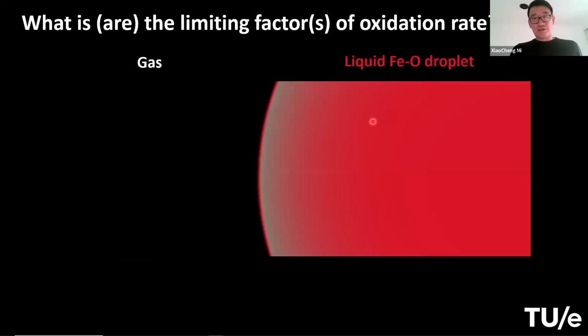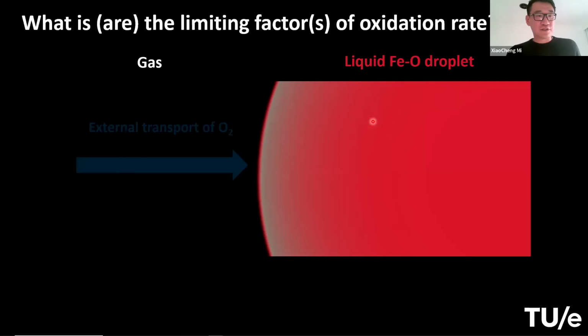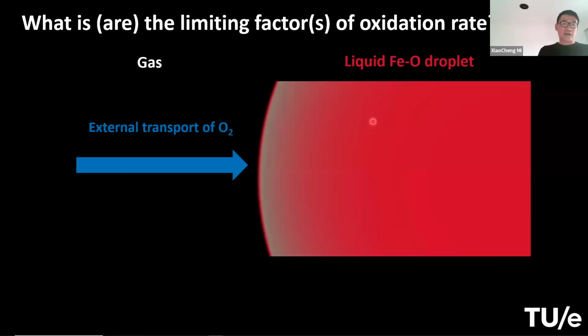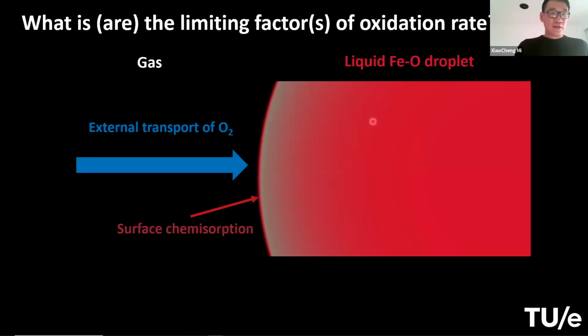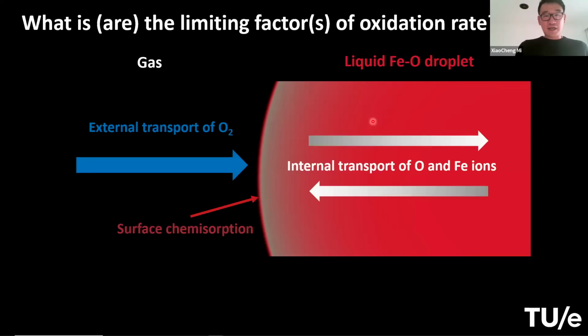And then in liquid phase, we consider the particle might be limited by a few factors, so that the oxidation rate is governed by the interplay among these factors. The first one is the boundary layer external diffusion of oxygen from the bulk gas to the iron particle surface. And then surface chemisorption is the second process. And inside the particle, there is also internal transport of Fe and O ions. And of course, there's a reaction between Fe and oxygen.